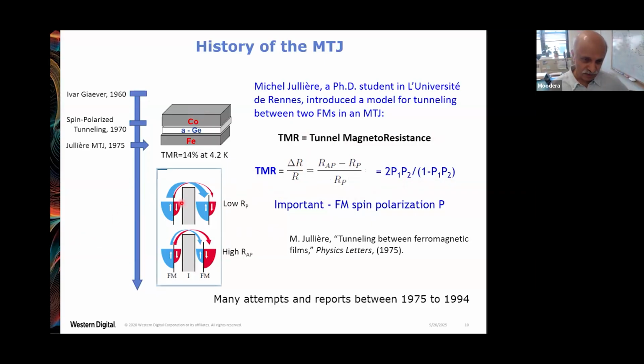Now, let me tell you the basic principle of this TMR. This is a two-band structure. In other words, this is the way the electrons are distributed in a ferromagnet. You can see here, this is magnetically pointing, say, upwards, and this is also magnetically pointing upwards. That means the number of spin-up electrons is very large here, and they can go into this one, which also has very large empty states. That means the current can flow very easily, a large current shown by the size of the arrow here. The minority spins also do the same thing because the spin is conserved. Nothing happens to the orientation of the spin. As a result, this is preferred.